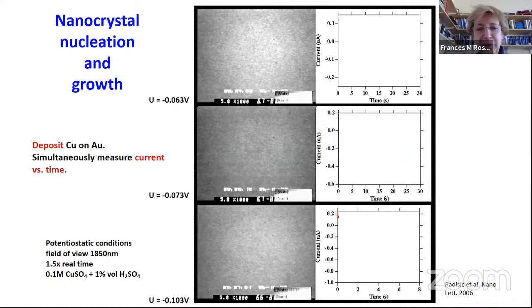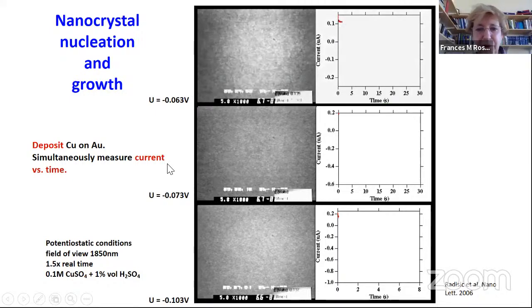Okay, so the first thing I want to show you is something that I found especially interesting at the time. One of the motivations for doing electrochemistry was, as I mentioned, how does copper grow when you're trying to make an interconnect for a microelectronic circuit? So here's an experiment where we're looking down onto a gold electrode. You can't really see the structure of the gold electrode. It's just this kind of fuzzy gray background. But we're in copper sulfate, sulfuric acid solution, and we're applying a constant potential with respect to a copper reference electrode. And we're going to look at what happens.